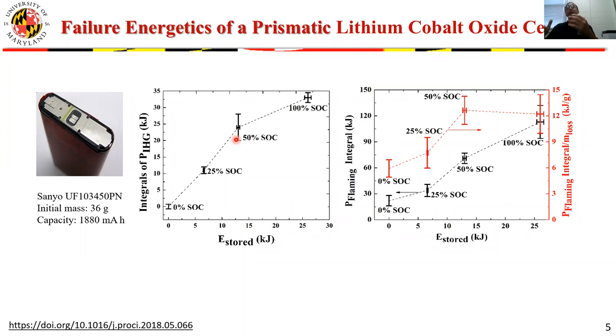So basically, if you were to retain all these materials inside, because we're measuring what's actually produced inside the cell, you would expect a straight line here. And we actually showed in our calculation that it's close to a straight line. But because you eject those materials from the cell, and we don't measure that part in this particular test, we do measure it in another test that I'm about to mention, you're going to have that sort of flattening out.